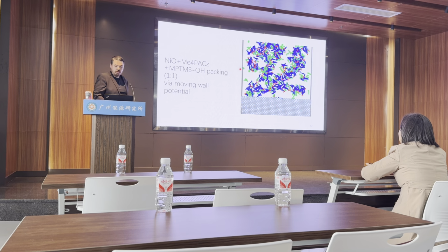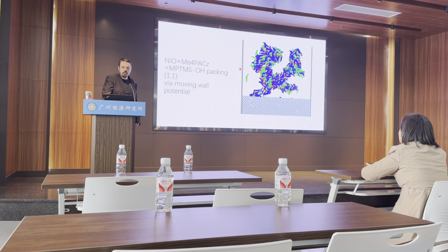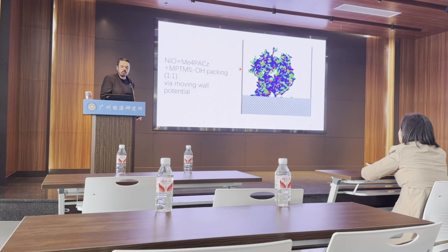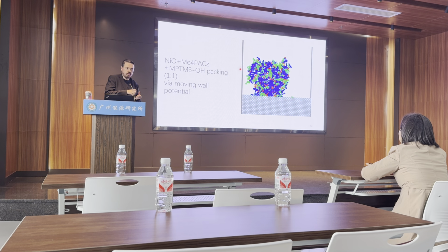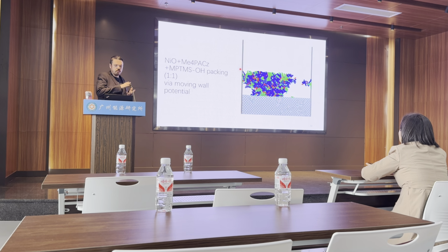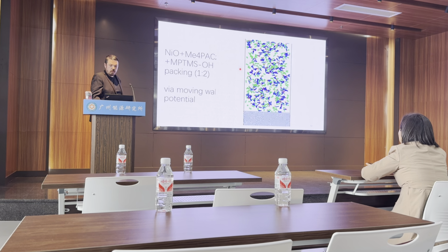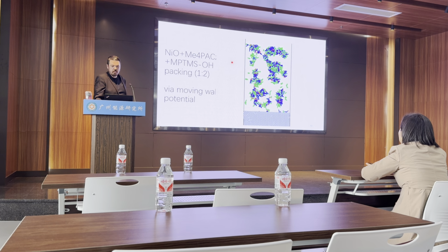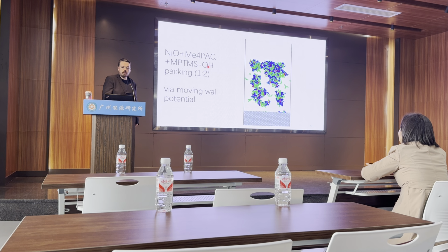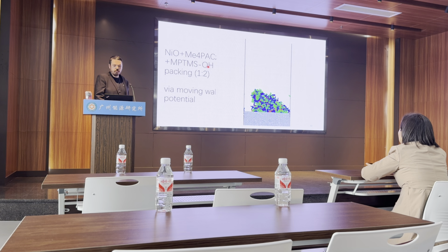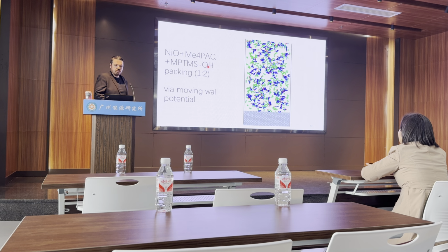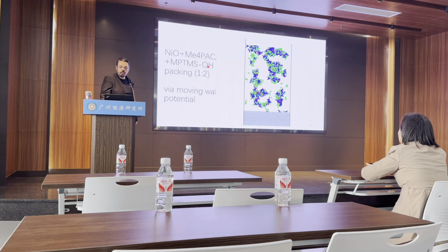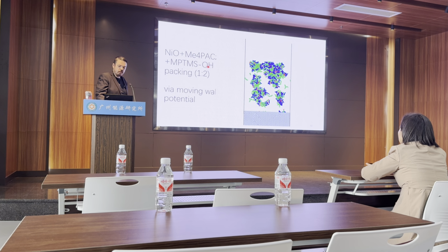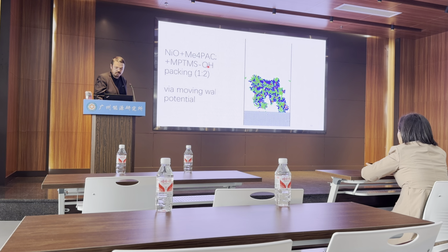So that's just the Me4PACz. Then when we mix it with MPTMS-OH, you can see the behavior is quite different. It clumps up a lot harder and a lot denser. So you get a denser film. And if we double the MPTMS-OH, we get even stronger clumping actually. So we get a really dense material. So this is all done via moving wall potential. Not many people have done this before, so we're kind of first on this almost.